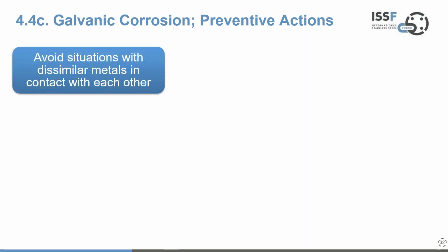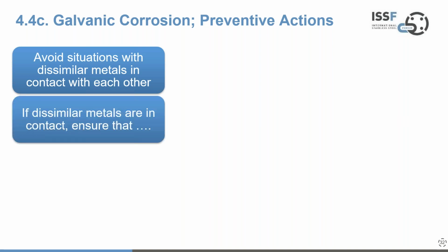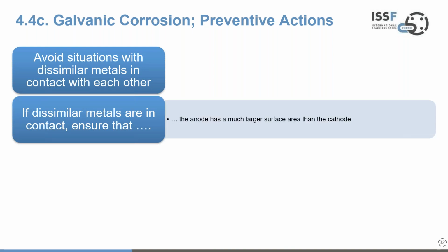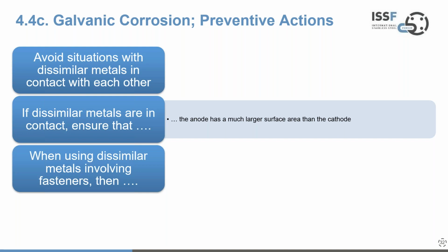So in terms of galvanic corrosion, what do we do? So first and foremost, try and avoid situations with dissimilar metals in contact with each other. And the two nuts is a classic case in point that was perfectly preventable. But if dissimilar metals are in contact, ensure that firstly, the anode has a much larger surface area than the cathode, because if you're going to sacrifice a product, you want it to have a large surface area. So that's really important. When using dissimilar metals, however, you've also got to think about fasteners.